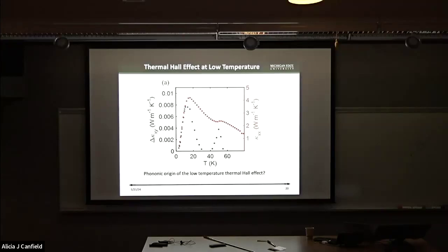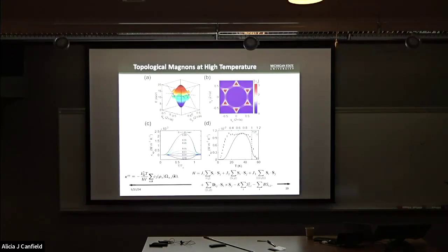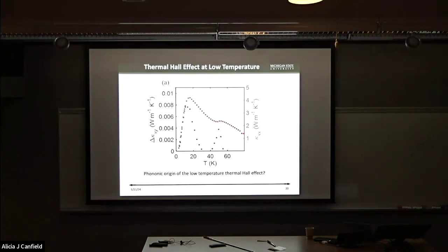But before we address this question, here we plot the difference between these experimental results and the calculated results as a function of temperature. The result is shown by this blue dot. And we can see that there are two peaks. We can just forget about the high temperature peak because this is an artificial feature. Our thermal Hall conductivity was calculated based on the mean field theory, which could not capture the fluctuation phenomena near the phase transition. Okay, so again, this is an artificial feature.